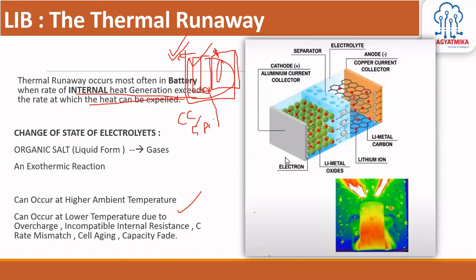So don't take it for granted that the thermal runaway condition can occur only at higher temperatures or on sunny days. It can occur even at lower temperatures if you are not managing the different properties of the cell. These things are to be considered. Then it leads to the thermal runaway process where the separator tearing will happen. If it gets torn, the electrolytes are volatile, they form gases and get expelled as gases. The separator gets torn off and the two electrodes come in contact with each other, so definitely this will cause an internal short circuit.